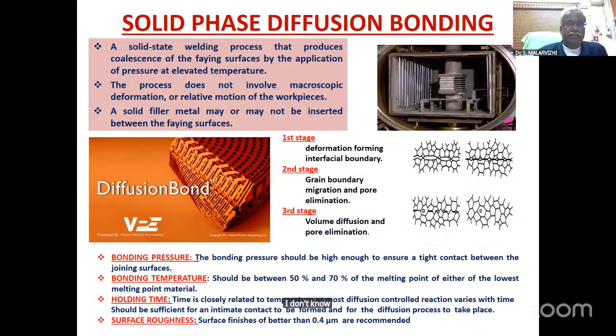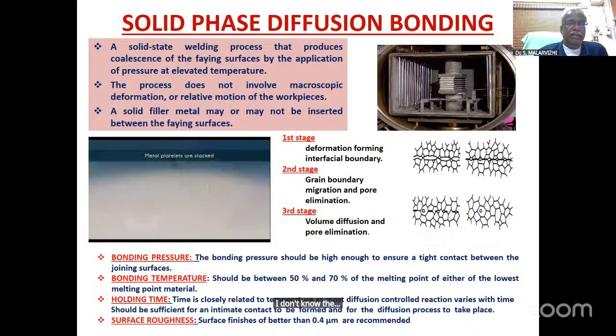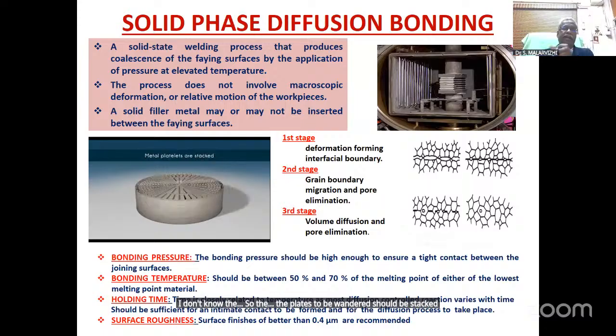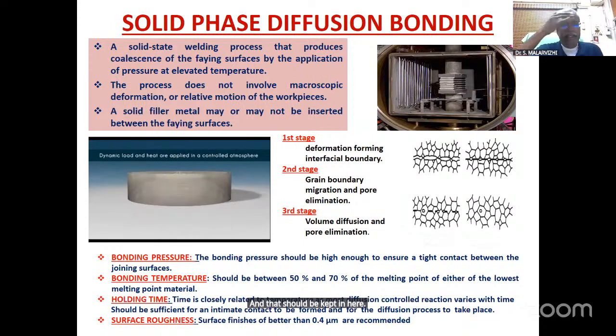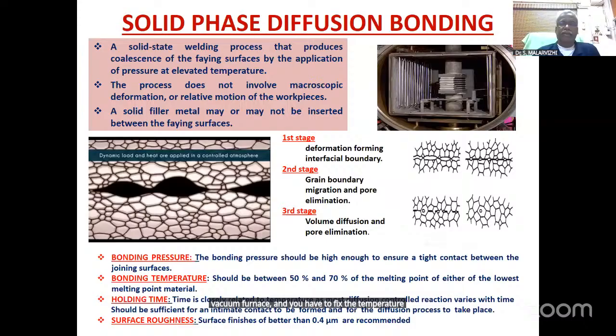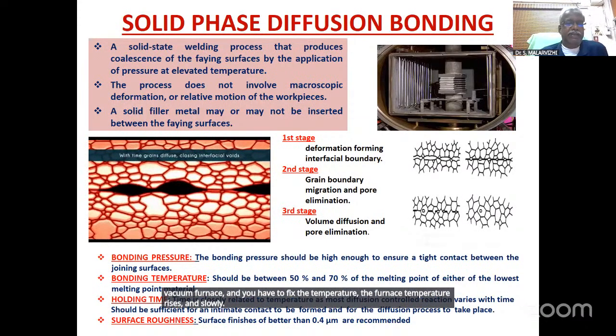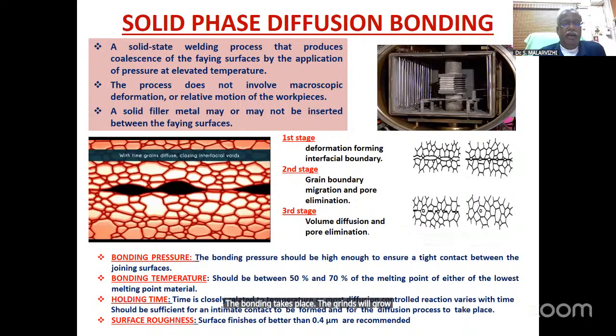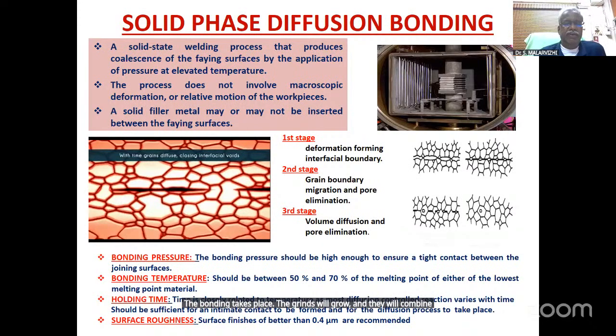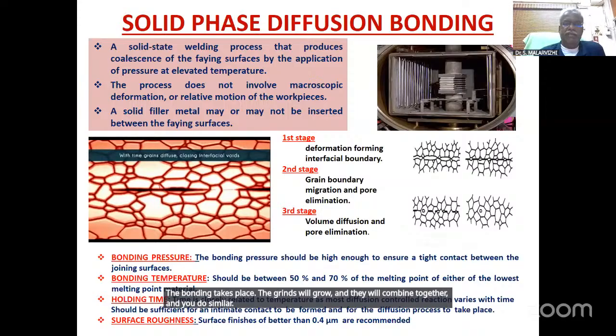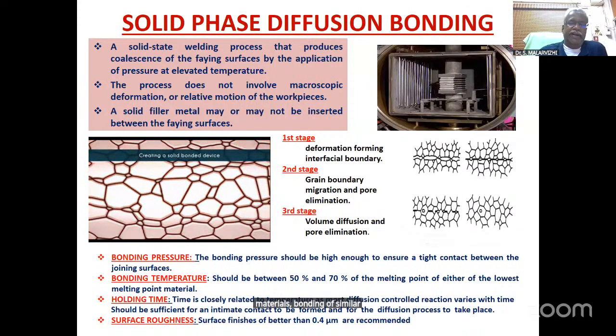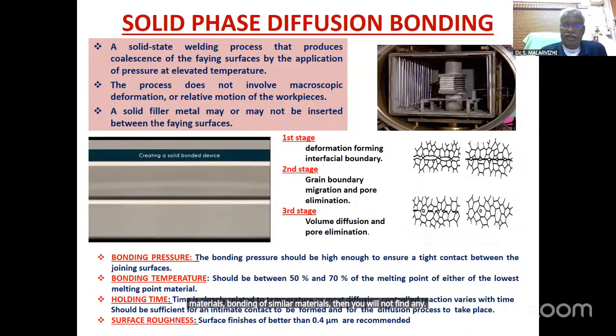And the plates to be bonded should be stacked one over the other, and kept in a vacuum furnace, and you have to fix the temperature. The furnace temperature rises, and slowly the bonding takes place. The grains will grow and they will combine together. And if you do bonding of similar materials, then you will not find any interface between the materials here.